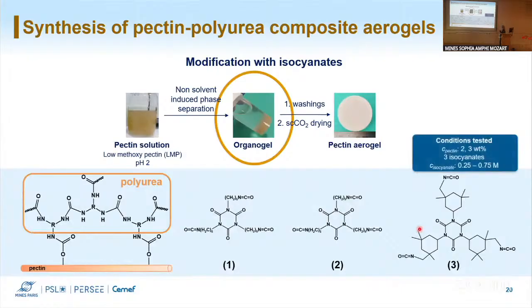We had these 3 isocyanates, so I will be referring to them as polyurea 1, polyurea 2, and polyurea 3. And we varied for this project the concentration of pectin in the starting solution and the concentration of isocyanate to get different content of isocyanate inside our material.